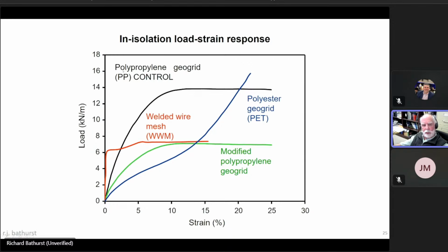We removed every second transverse member, and we managed to reduce its strength and its stiffness by half by doing that. And then this material was paired with the welded wire wall test because they both had the same strength, but the welded wire was much stiffer. So this allowed us to isolate the effect of the reinforcement stiffness on reinforcement loads.